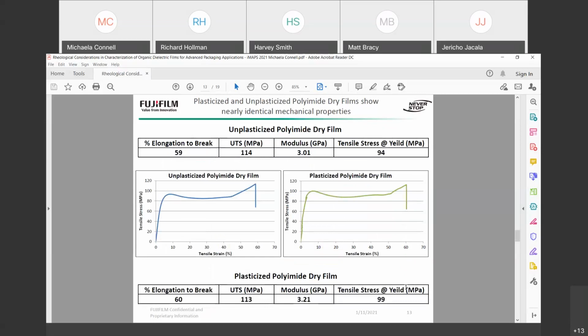Okay, so now let's look at the other possible effects on the film. So here we have the stress strain curves, which post-cure have nearly identical results. So on the left, we have the unplasticized polyimide dry film. On the right, we have the plasticized. And the elongation to break, UTS, modulus, and tensile stress at yield were all extremely close, nearly identical, meaning that the diluents have no effect on the mechanical properties post-cure.